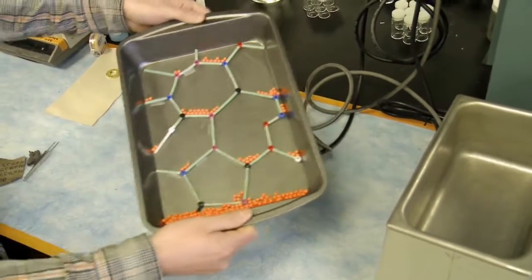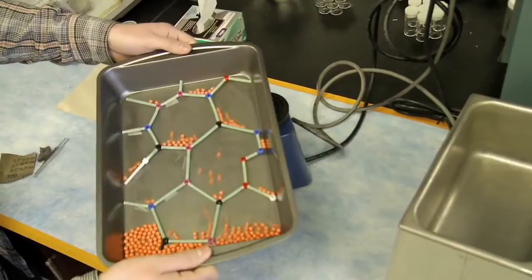One of the major findings we wanted to report was that these charge carriers moving through the organic semiconductor film could be trapped by grain boundaries in the material. And not so much that they were trapped on a grain boundary, but trapped by the grain boundary. Much in the same way that your dog is trapped in your yard by the fence and not on the fence.